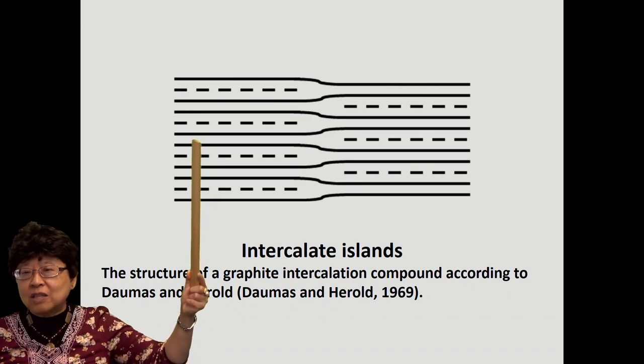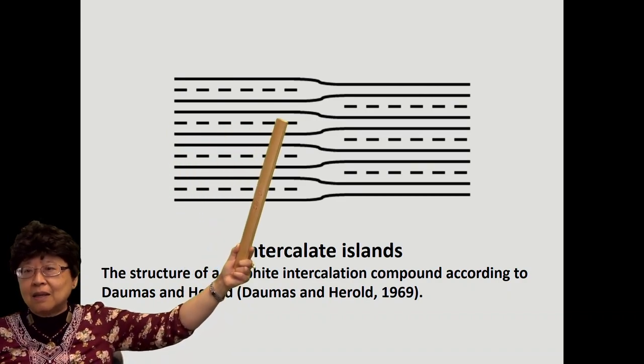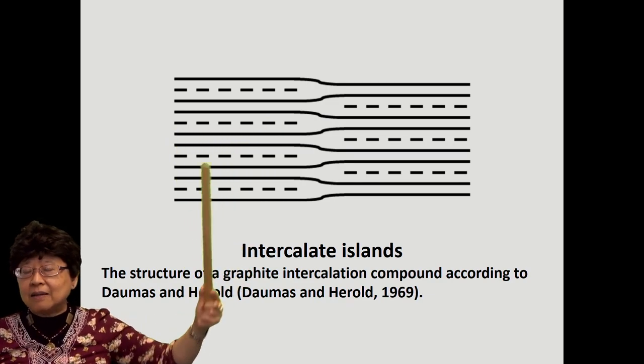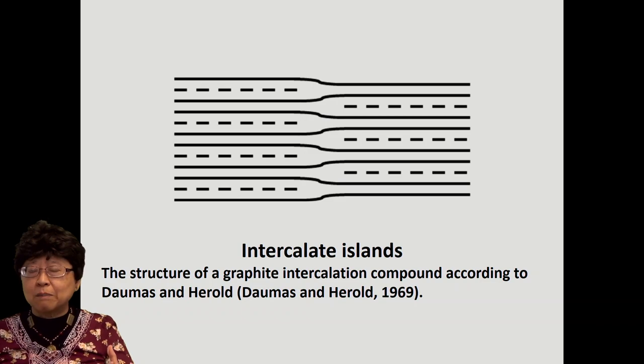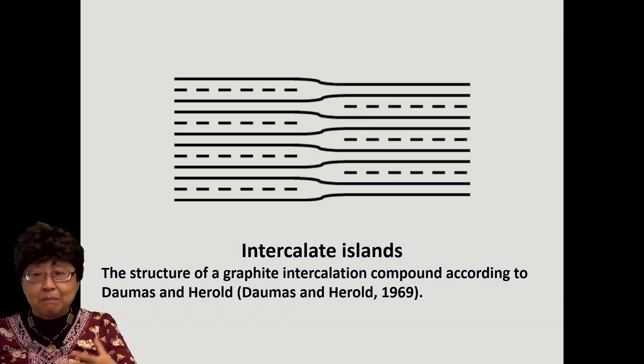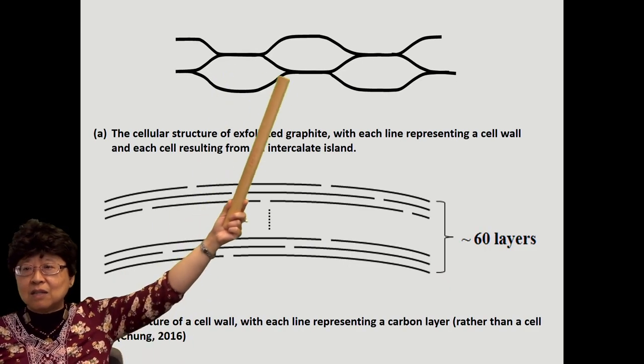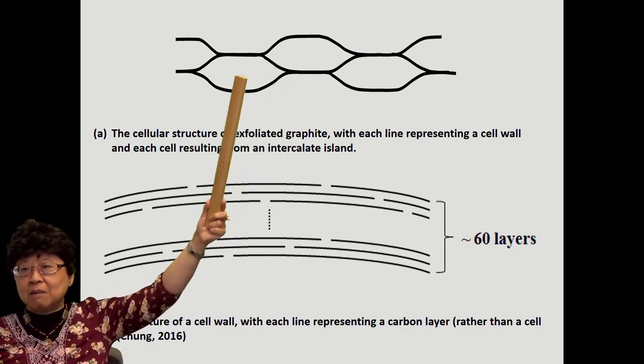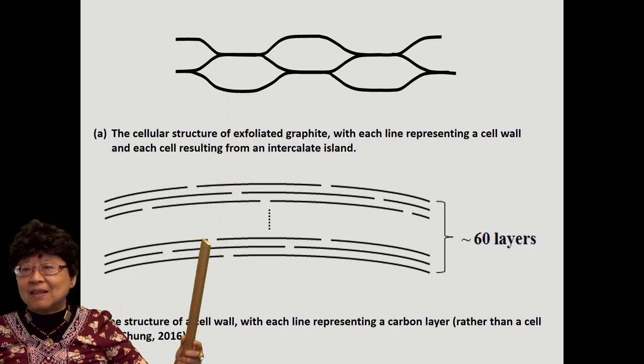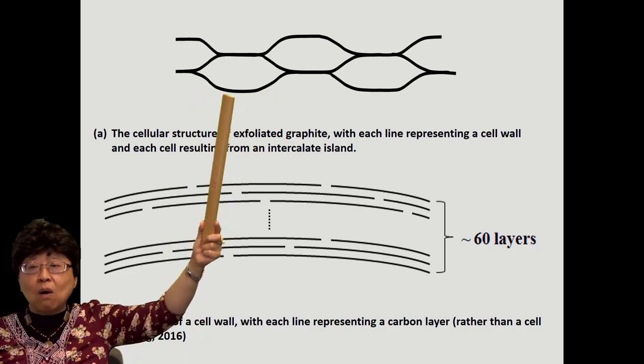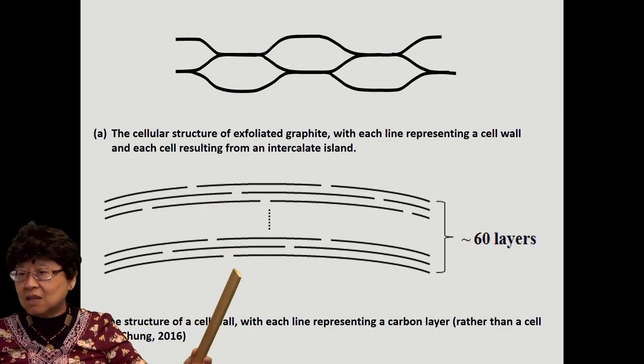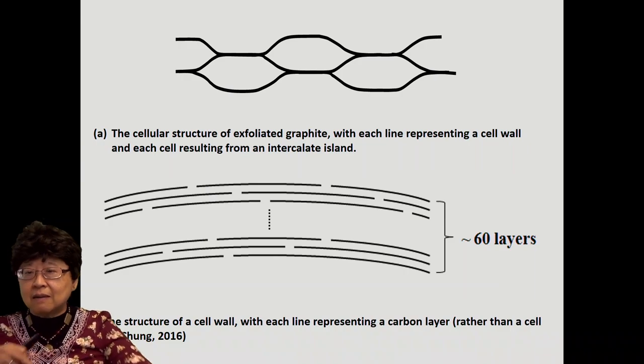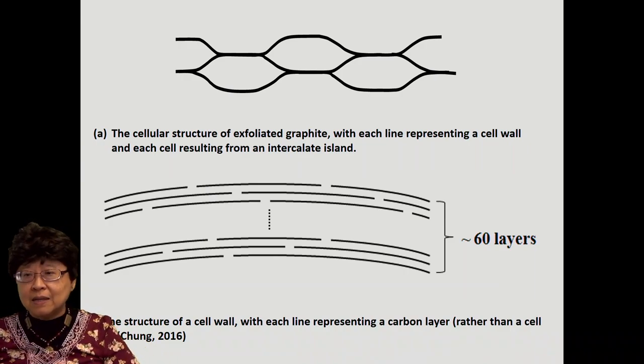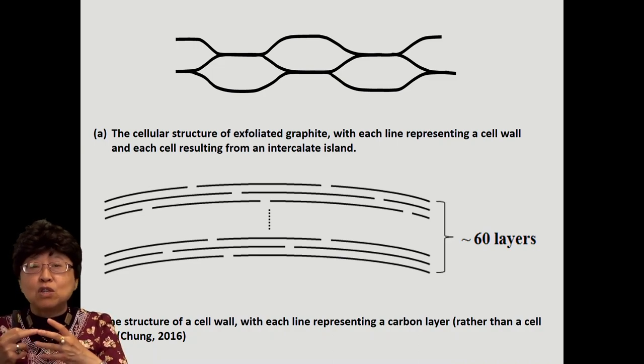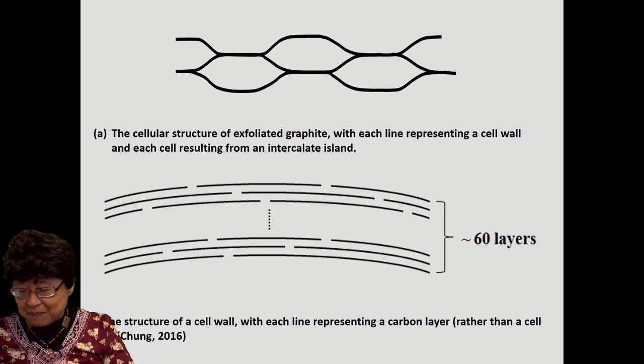And actually, the intercalate is in the form of islands, shown by these dashed lines. And the ballooning effect that I talked about involves these islands becoming balloons. And that's the exfoliation process. And this is the cellular structure showing these balloons. This is the cell wall. And the cell wall actually consists of, say, 60 carbon layers. And the carbon layers can slide relative to one another very easily. Thus, the balloon wall can be stretched a lot, and that's why it can balloon.